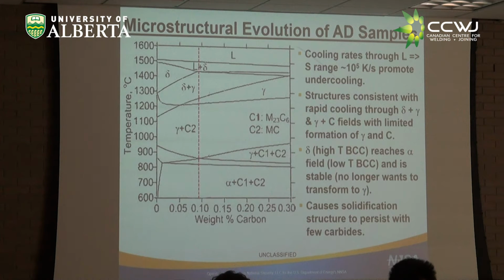So if we go back and look at the microstructures, and bear in mind the little spot weld experiments we talked about, plus the thermal cycling, what it looks like is the structures that are formed, I can't tell you why, are consistent with rapid cooling through forming liquid plus ferrite and then ferrite, but rapidly cooling through this region here, the two-phase ferrite plus austenite, austenite, two-phase austenite plus carbide, down here into the alpha. Now, delta and alpha are just designations for the high temperature ferrite phase, BCC phase, and the low temperature BCC phase.